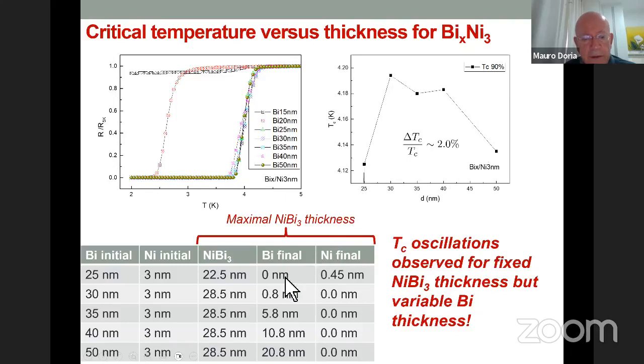And the reason is that in 25, you deposit 3 nanometers of nickel onto 25 of bismuth. All the bismuth is consumed in the formation of this superconducting compound, nickel bismuth 3, and there is some nickel left. So we discard this data and begin with 30 nanometers, where we have no nickel left over. Everything is consumed to make nickel bismuth 3.